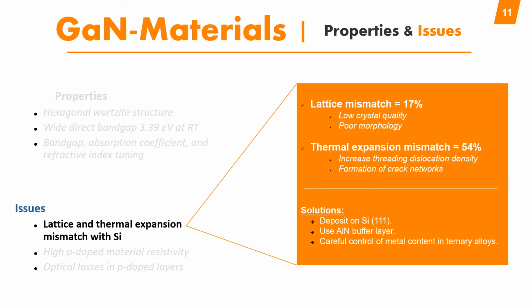So some solutions for deposition, not all solutions, and not all of these that I'm going to say are efficient, but some solutions are to make use of a nucleation or buffer layer, the most common one being aluminum nitride on top of the silicon substrate. This aluminum nitride can block the interdiffusion of gallium inside silicon and silicon inside gallium, which is not acceptable, as this interdiffusion allows for the creation of leakage current, which is not wanted at all for device operation. So the aluminum nitride buffer layer can help reduce the crack network and help reduce the stress in the layers.